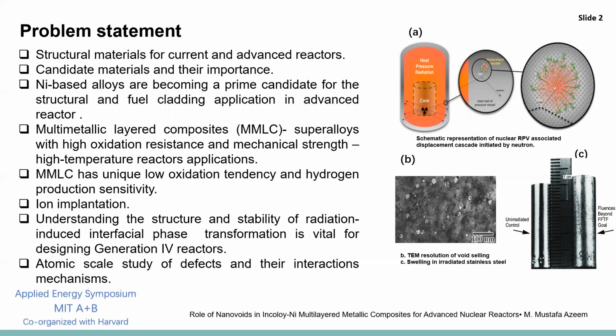There are numerous candidate materials for the generation 4 reactors, out of which ferrite and martensite have demonstrated increased radiation stability and excellent mechanical properties. In our model, we have used nickel-based solid solution alloys consisting of nickel, iron, and chromium in combination with varying composition in terms of iron and chromium. Then we can have Incoloy.